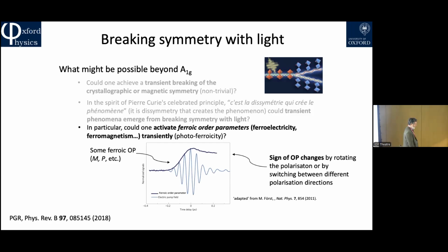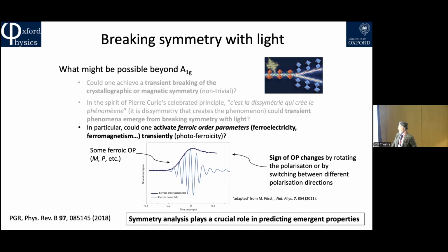So if you pump in all the different modes, you can only couple. But if you couple to the degenerate mode, the mode that has two possible directions of the order parameter, that you can pump, then you can rectify a mode that is not totally symmetric.